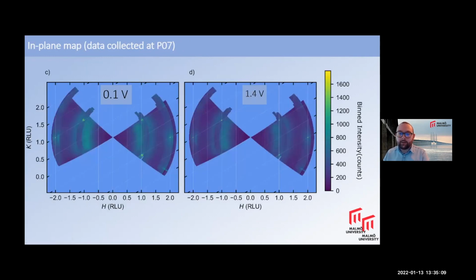Okay, so we collected some in-plane maps. So this shows the in-plane map at the lower, or the more negative potential, so it's 0.1 volts. This is versus the reversible hydrogen electrode. And you can see that you have these spots around the CTRs due to the surface reconstruction. And if we go to a high potential, and we really have to go to quite a high potential actually, you can lift the reconstruction, and then you just have the CTRs.